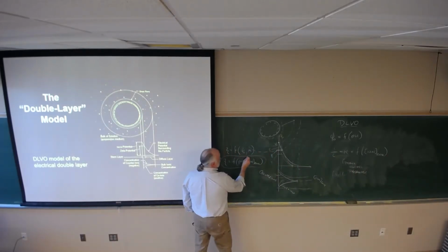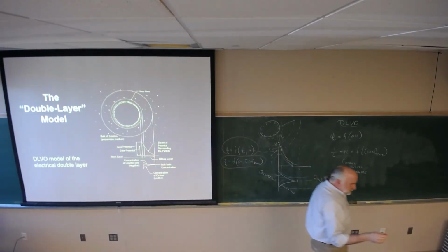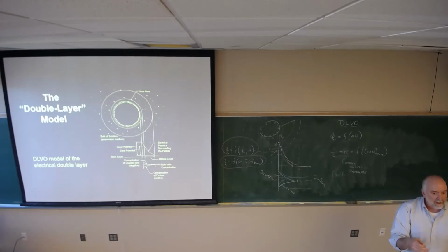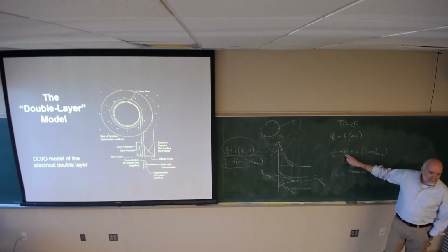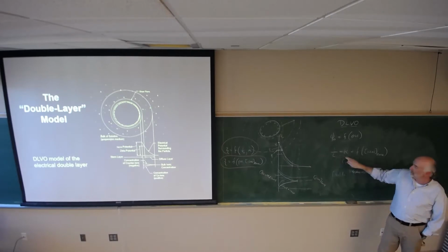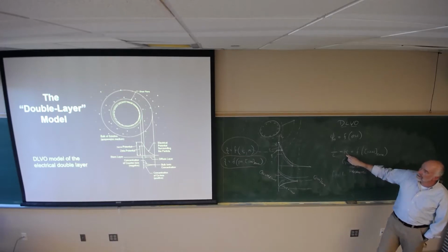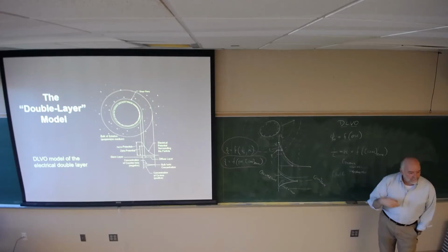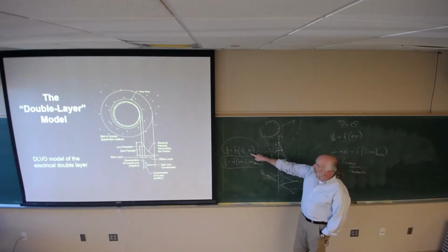This is technically more correct, all right? The top one is technically more correct. Zeta potential is ultimately a function of pH. It is directly a function of the Nernst potential, and then it is a function of the Debye-Huckel parameter, the inverse thickness of the double layer, right? So if this gets larger, zeta potential decreases. Okay, so technically, this is correct, right?